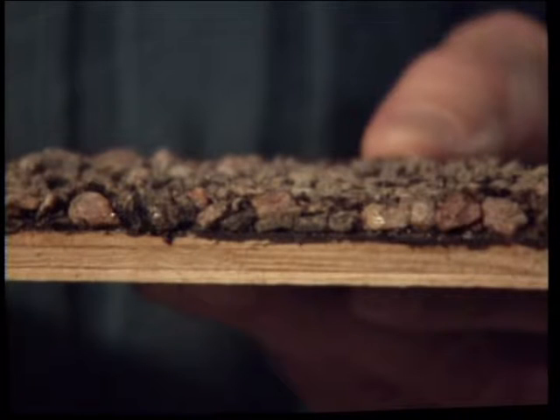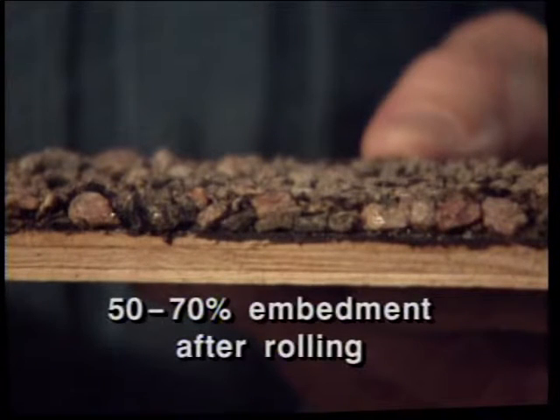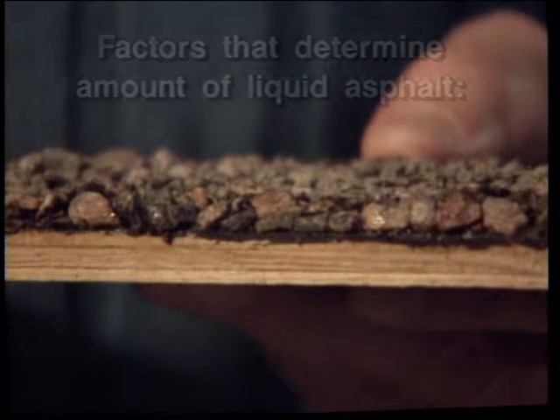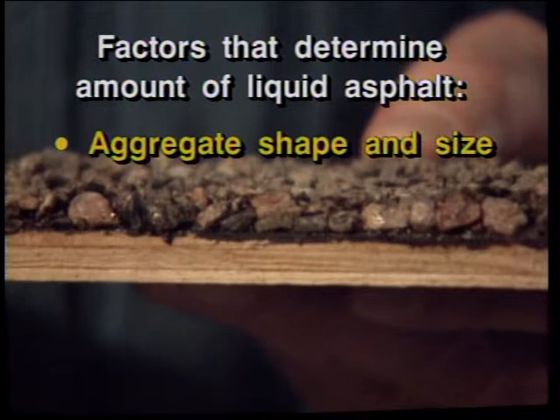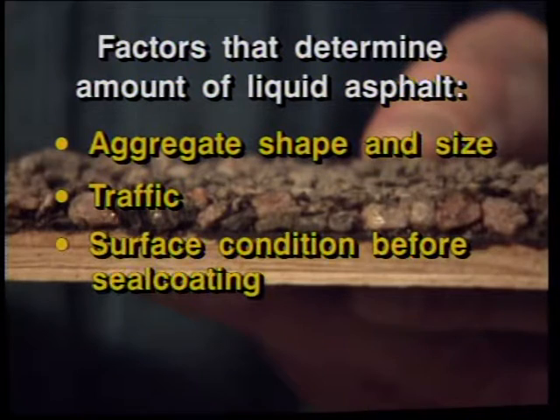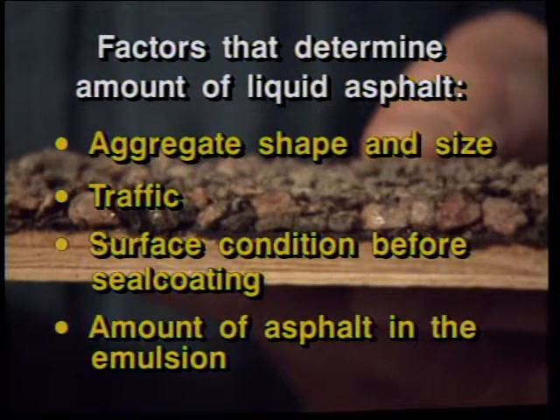of each to use. Determining how much aggregate to put down is pretty straightforward. Your goal should be a layer 1 stone deep, like this. But figuring out how much emulsion to use is a little more complicated. The goal should be to put down enough emulsion so that 50 to 70% of each stone is embedded in asphalt after rolling. To achieve that, you have to take several factors into account: the shape and size of your aggregate, the amount of traffic that uses the road, the condition of the pavement surface before you seal coat, and the amount of asphalt in the emulsion you're using.